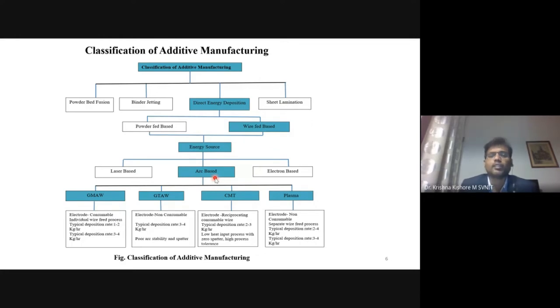And what are some conventional arc based heat sources we know? MIG welding, GMAW, TIG welding, GTAW, the most advanced version of MIG welding, which is cold metal transfer, and people are also using plasma arc welding. These are the typical deposition rates we can achieve, mentioned here. In MIG welding, we can achieve 1 to 2 kg per hour. In TIG welding, 3 to 4 kg per hour. In cold metal transfer, 2 to 3 kg per hour. And in plasma arc welding, 2 to 4 kg per hour.